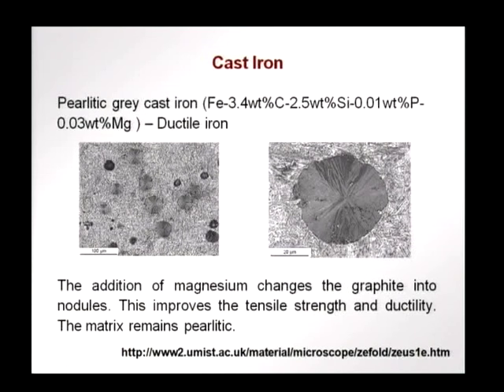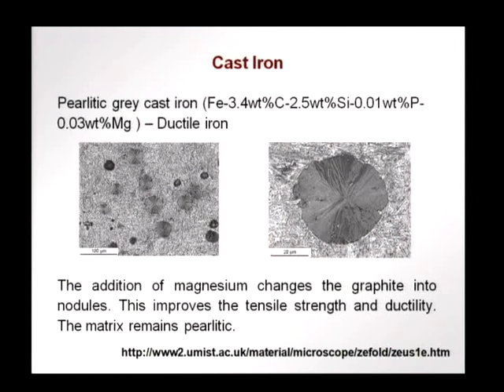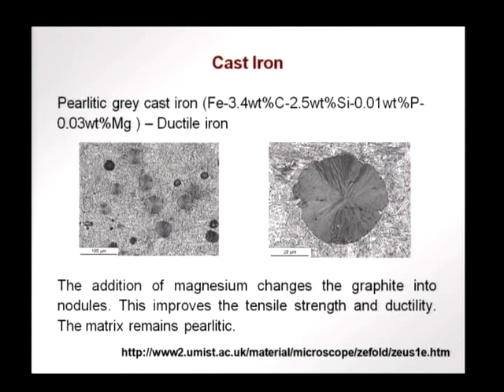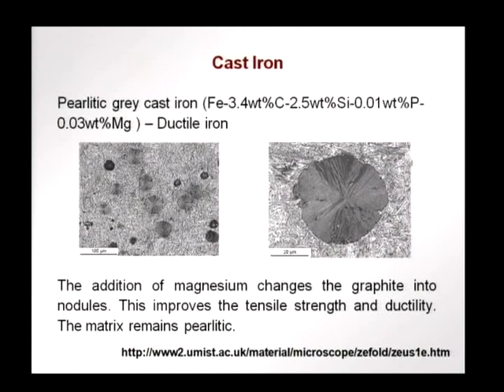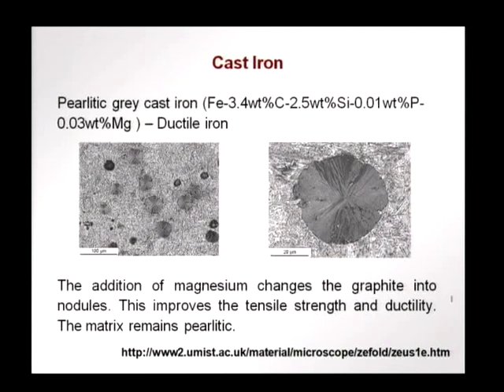In ductile iron, magnesium is introduced in a small quantity of 0.03% by weight. The addition of magnesium changes the microstructure — the graphite, instead of being flakes, now becomes nodules. So you do not have large defects through which the crack can run. You have these isolated pieces of graphite distributed in the pearlite structure. The pearlite continues to exist with the grainy pearlite layers on the outside. This gives rise to higher tensile strength and ductility compared to low phosphorus cast iron.